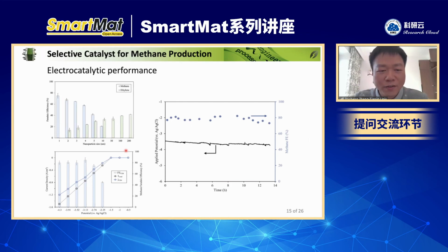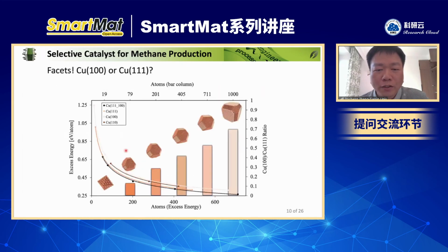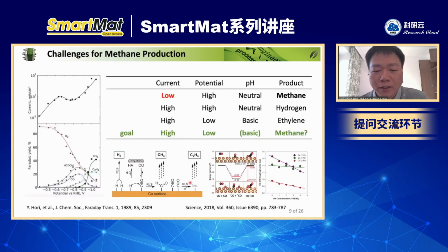Okay. Thank you. Thanks for your detailed response. So I think especially for the mixed phases for the small nanoparticles or even bigger sizes, there is just a boundary between different facets. Maybe for the mixed facets, we facilitate the formation of the CC coupling, because as you also mentioned, C2 products, ethanol, ethylene, refer to CC coupling. For one facet is CO and another facet another CO, maybe asymmetrical CC coupling or symmetrical CC coupling.